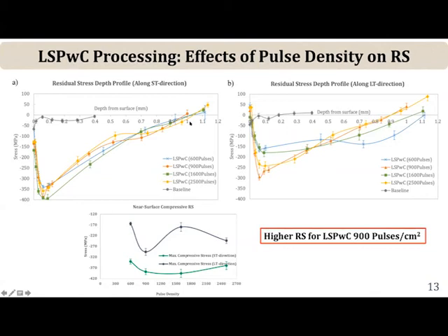Now, if you did this with the tape, then the surface compressive stresses would be much lower than the case without, when we don't use a coating. But the magnitude we found was that much lower. So in fact, when you do this without a coating, you can get much higher levels of compression compared with when you use an ablative tape. Based on this study, he chose 900 pulses for processing all the remaining samples.